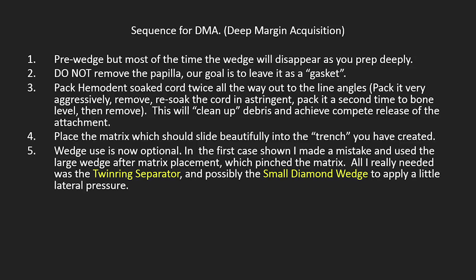If you have a deep margin acquisition case and there's just nothing to hold the wedge, and the wedge is smashing the matrix, you don't need a wedge anymore because the separator provides more tooth separation. The separator provides more tooth separation than the wedge. So you don't have to use a wedge. You just need to make sure that the matrix is laying nicely against the tooth. And once you create that little trench for deep margin acquisition, 90% of the time, it's a perfect seal. Put the bulk fill flowable down, cure it. Now we're not going to worry about having a bunch of extrusion.